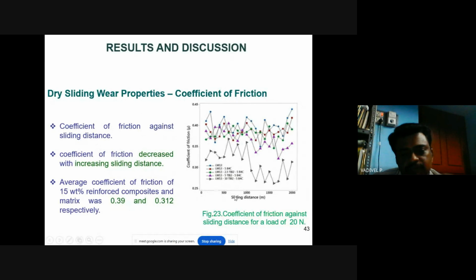The next plot is between the coefficient of friction and the sliding distance. The coefficient of friction decreased with increasing sliding distance. We know the value of friction in brakes, the friction between the brake drum and the brake shoe. Without friction, the brake will not stop and the vehicle will not stop. For that purpose we have undergone this friction study. The average coefficient of friction we obtained is 0.39 and 0.312 for the 15 weight percentage reinforced composite and the matrix respectively.